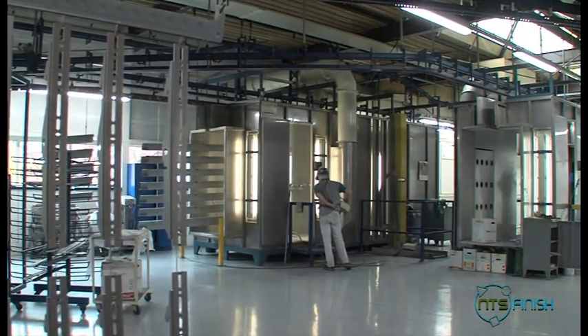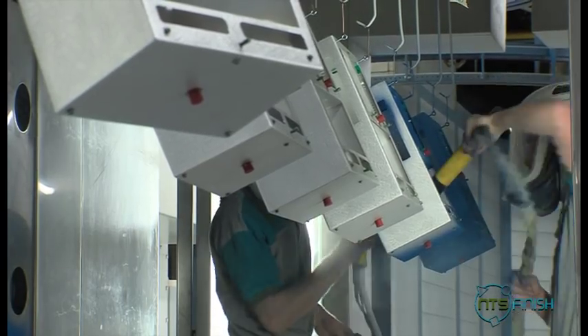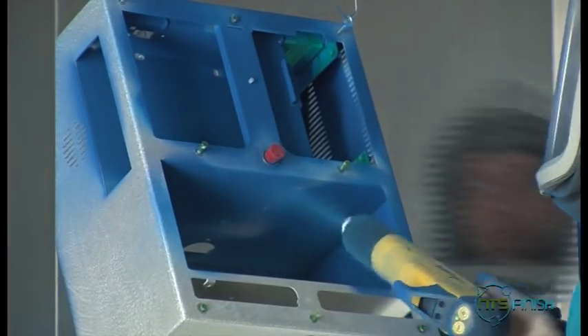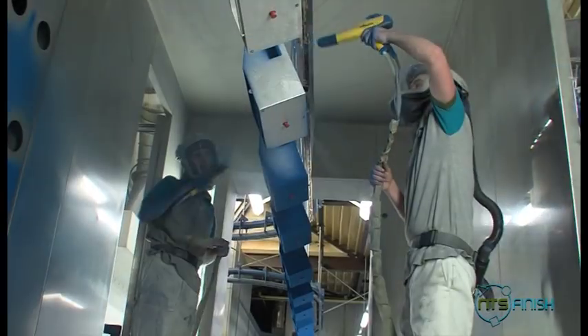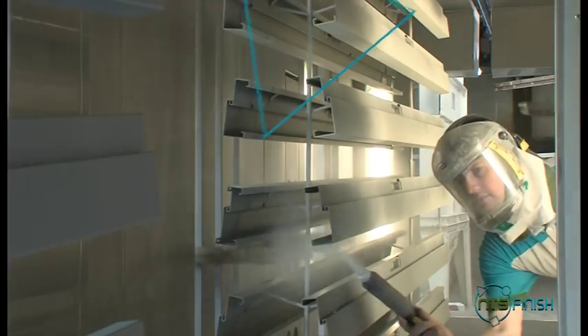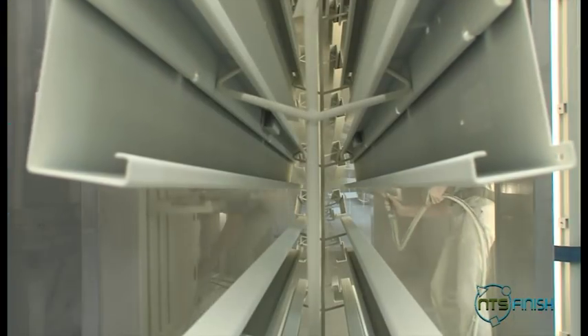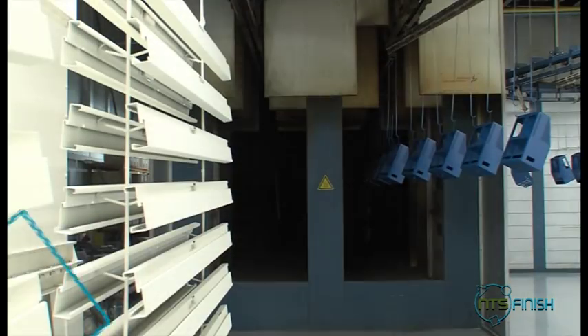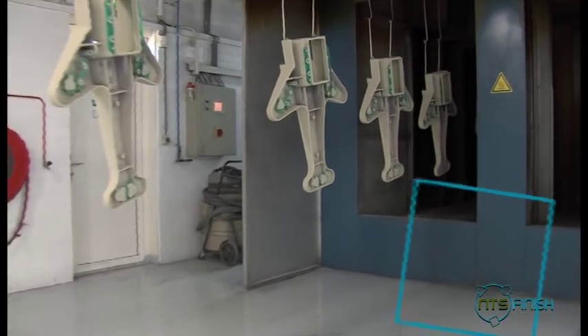Our powder coating lines are equipped with automatic spray guns, manual spray guns, product recognition, cyclone and a post-production filter. Here, the negatively charged paint powder is sprayed on the positively charged metal. A major advantage of powder coating is the durability and therefore the quality of the coating. Heavy metals or harmful vapors are out of the question. In the muffle, with a temperature of 160 to 210 degrees, the powder melts to a UV-resistant smooth coating.